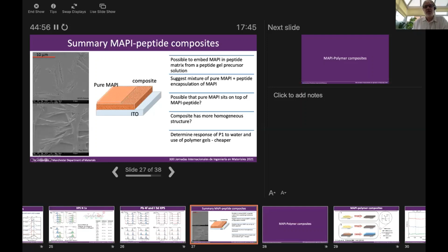So we think that the structure is something like this, that we've potentially got our ITO substrate. We have the composite layer and then pure MAPI sitting on top. And one of the reasons we think that is that the degradation appears to happen at the surface. So we're seeing loss of this pure MAPI material from the surface of the composite.